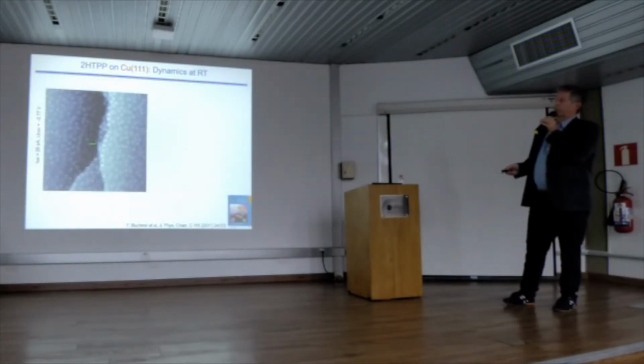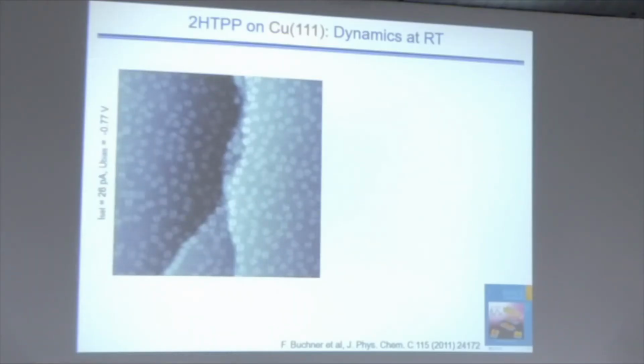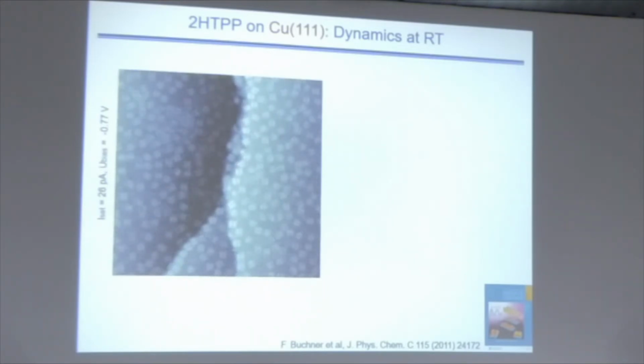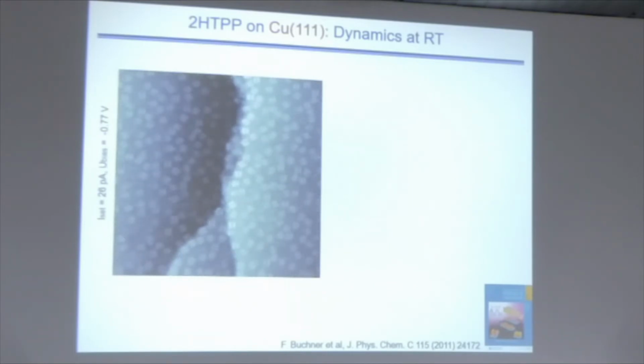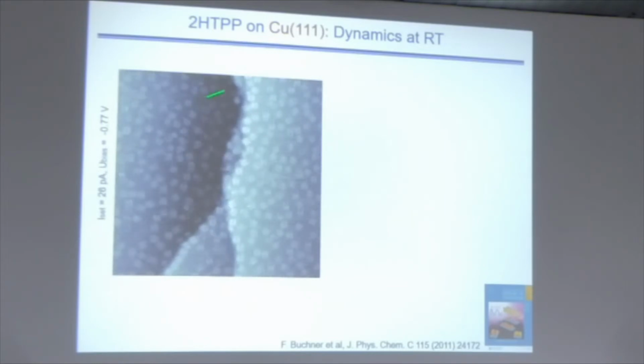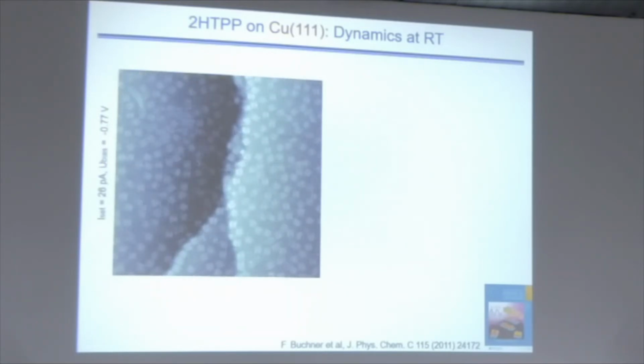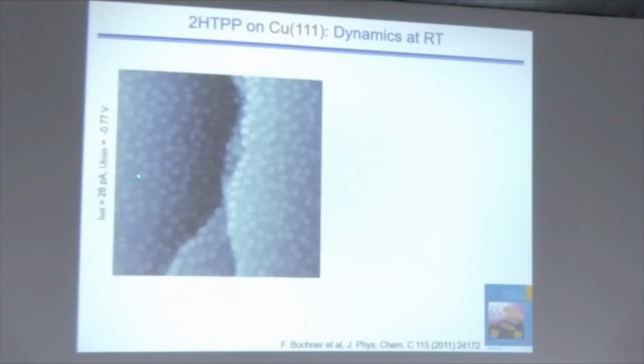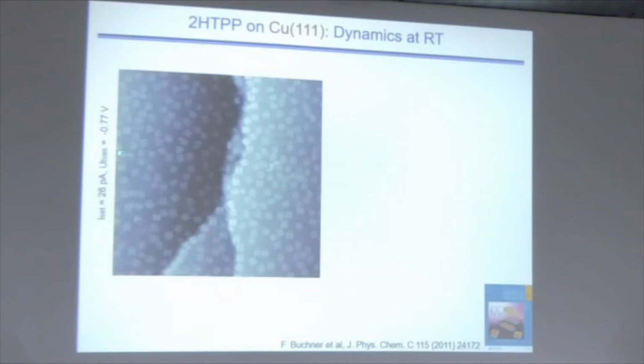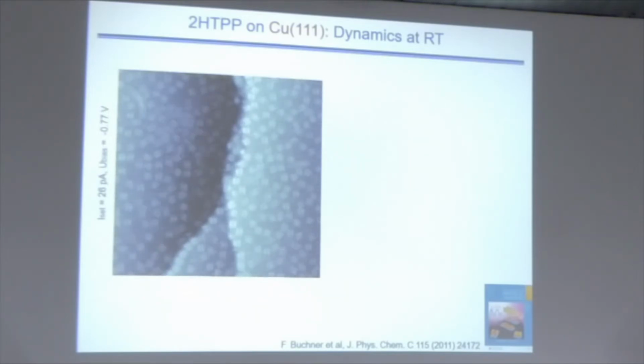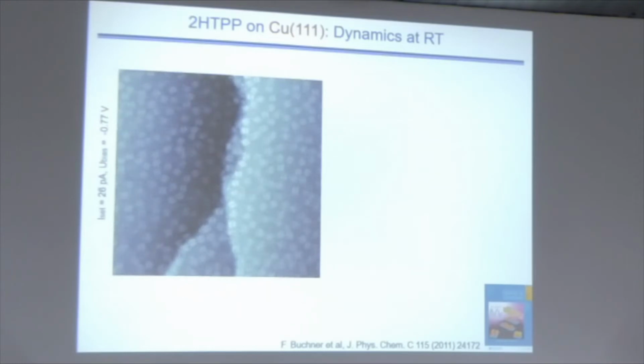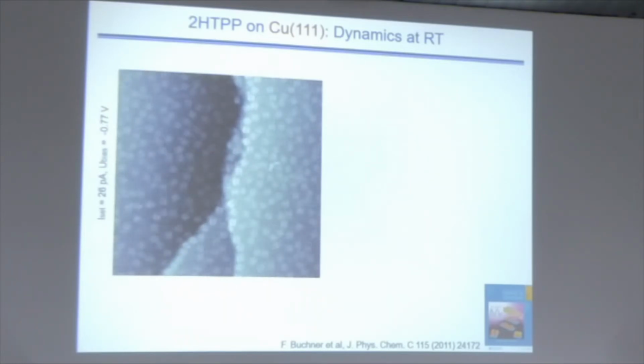Then you saw that beforehand, this was my introductory slide, that the molecules move on the surface. These are the molecules. How do we do that? So we take a movie. That means we measure STM image after STM image after STM image of the same area on the surface, and then we add these images one after the other, like in a frame of a movie, and then we have an endless loop, and these are, I think, 25 images, and then we show it like that. So it's a really super slow motion of the actual motion. And what you see is they move, but they don't move randomly. They move here up and down. This one here. And these move, the ones that are oriented like that, only in this direction. So the molecules, they behave like a train on rails. If you are in the rails, you just can move in the direction of the rails. And this is what is happening here.